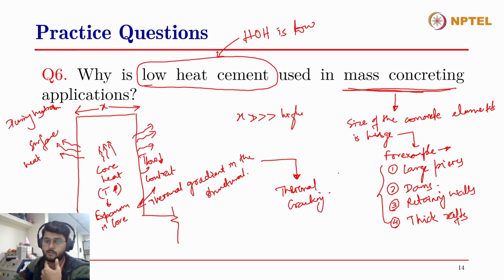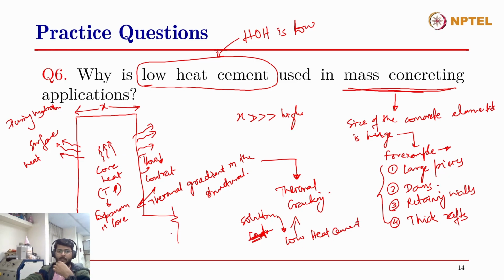So what is the solution to this? We introduce low heat cement. The solution is low heat cement. When the heat released in the cement is very low, the thermal gradient will still be present because the surface is still exposed to the atmosphere, so it will have a lower temperature, while the core will have a slightly higher temperature, but the thermal gradient won't be sufficient to accelerate the cracking in the structure. Therefore, we want to use low heat cement.